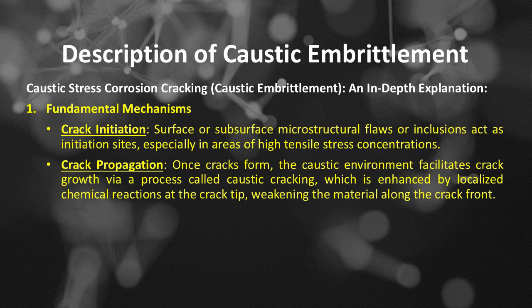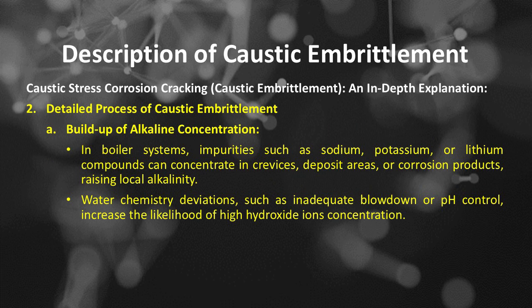Crack initiation. Surface or subsurface microstructural flaws or inclusions act as initiation sites, especially in areas of high tensile stress concentrations. Crack propagation. Once cracks form, the caustic environment facilitates crack growth via a process called caustic cracking, which is enhanced by localized chemical reactions at the crack tip, weakening the material along the crack front. Number 2 is detailed process of caustic embrittlement.